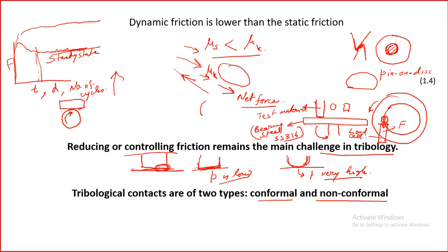This is what you will experience when you conduct a pin on disc test. When I look at the cross section of the pin surface, I will find that it has only partly worn out, and this side was not even touching. So this is a practical problem that you have to solve by some method so that you get as much contact as possible. But this problem doesn't exist with non-conformal contact, like a sphere on a flat surface, because whatever happens, there will always be a point contact. So you always get a good point contact.